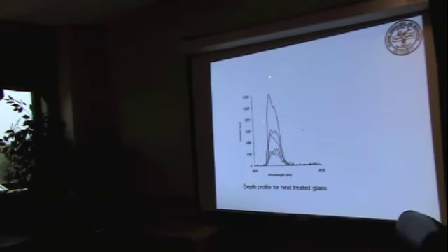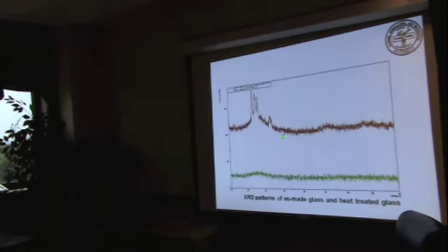And the same thing here, we made some depth profile, so you have more crystallized here. As you go deeper, they are less. And I will show you some X-ray diffraction measurements to show you that yes, it does have crystals. If you don't have crystals, that's what you get. If you have crystals, you see the sharp spikes.